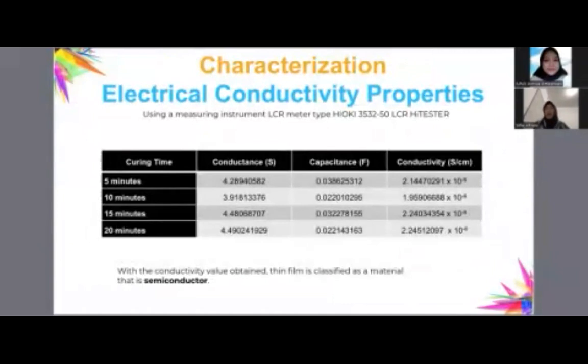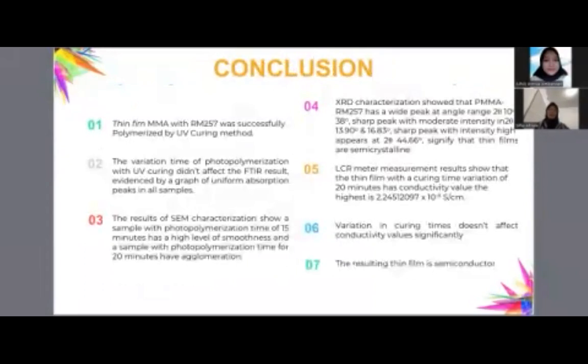Electrical conductivity is characterized by measuring the resulting thin film using the LCR method. The measurement produces the conductance and capacitance values of the thin film. Based on the data in this table, the thin film with a curing time of 20 minutes had the highest conductivity value compared to other samples, but the variation in curing time did not significantly affect the conductivity value of the resulting thin film. With the conductivity value obtained, the thin film is classified as a semiconductor material. And conclusion.